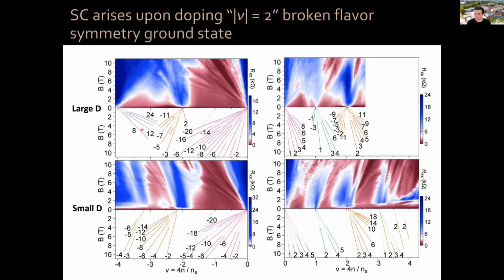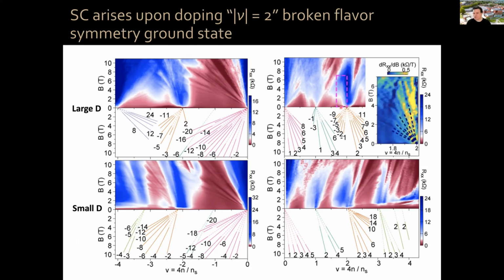Whereas if it points outward, you continue to do the same carrier doping. So in this case, electron doping, in this case, hole doping. If a Landau fan diagram points inwards here and outwards there, then you have both electron doping and hole doping out of this nu equals 2 many-body ground state. And that region here, which has Landau fan diagram pointing inwards, it's key to understand the origin of